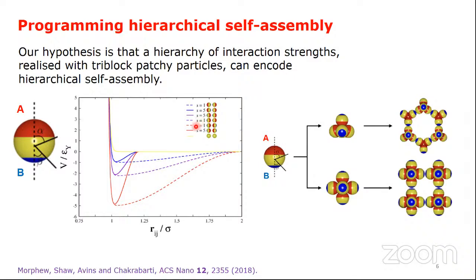Our hypothesis is that a hierarchy of interaction strengths realized with tri-block patchy particles can encode hierarchical self-assembly. Here, the patches on the opposite poles are labeled A and B. An A patch makes strong bonds with another A patch. The BB bond is weakest. A bond between patches A and B is not ruled out here, but is of intermediate strength. We optimize the patch width and the range over which these patches interact along with the inverse Debye length by finding the global minima on the potential energy landscapes.